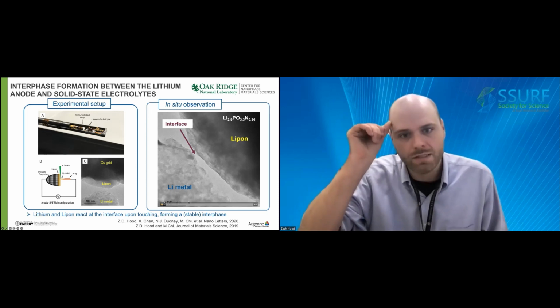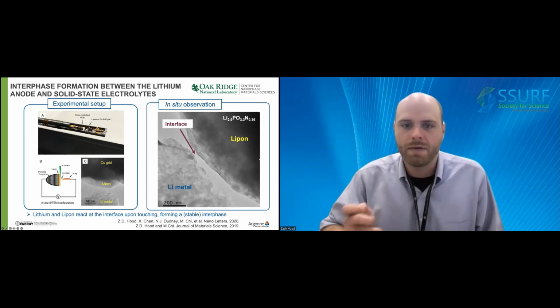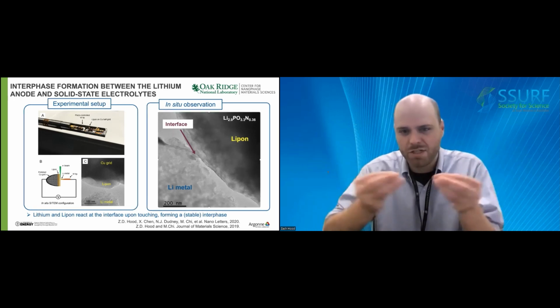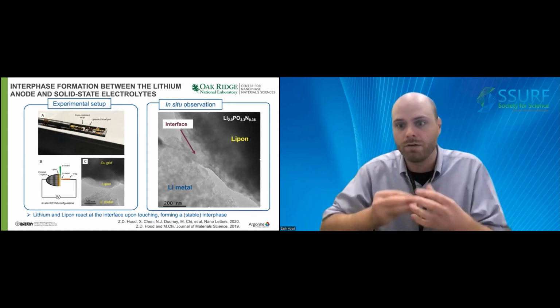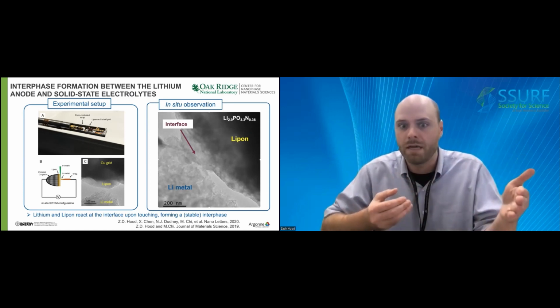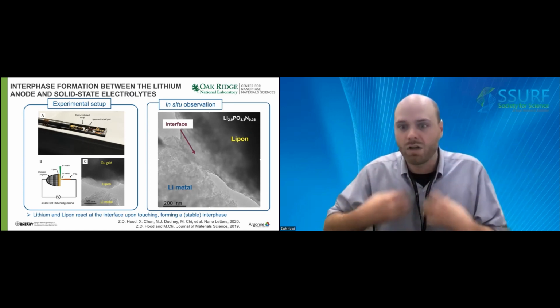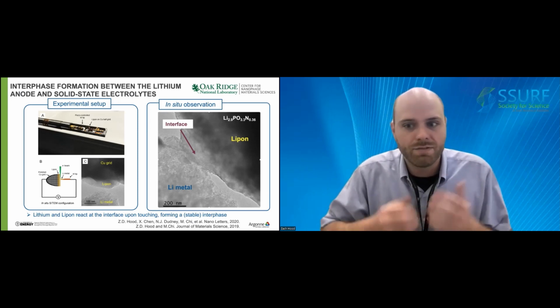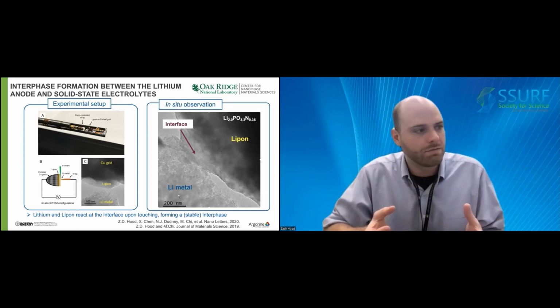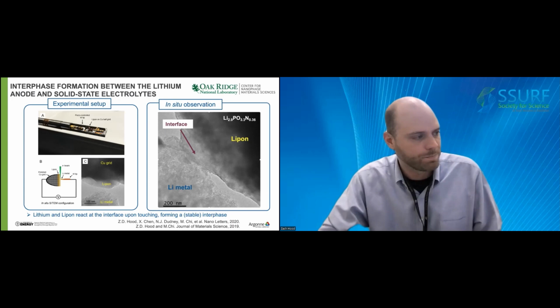So this is the interface that forms between LiPON and lithium metal. As you can see, upon touching the lithium metal and the LiPON solid-state electrolyte, there is an outward growth of LiPON towards the lithium metal anode, signifying a volume expansion of LiPON and the formation of what we call and refer to as the interphase.